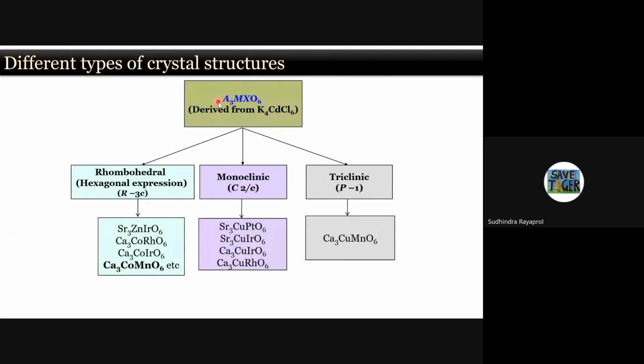And if you look at this A3MXO6 type of structure, there are different types of compounds which are available. Stoichiometrically, they look identical, but if you look at the structures, they have different structures. The moment you put copper at the tetrahedral positions, because copper is a Jahn-Teller ion, it can move out of its square prism coordination, and it reduces the symmetry of the system from rhombohedral, which is more with a hexagonal unit cell, to a monoclinic structure. So the monoclinic, as you know, has a low symmetry compared to hexagonal.